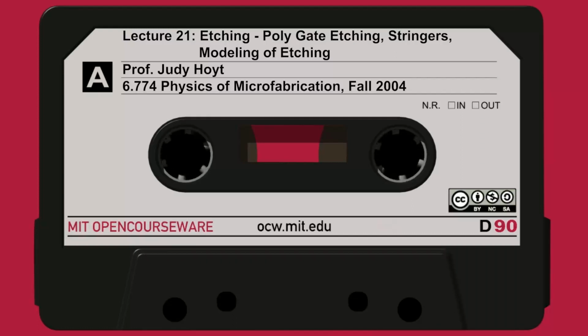People want to use metals. What's the concentration of electrons in a metal? I don't know, 10 to the 22 or 10 to the 23. It's huge. It's 3 orders of magnitude higher. So we need more electrons or more holes, more carriers in our gates these days. The way we do it is we take poly and convert it completely to silicide. This is called a fully silicided process. This is only in research. There's a lot of issues with doing this.